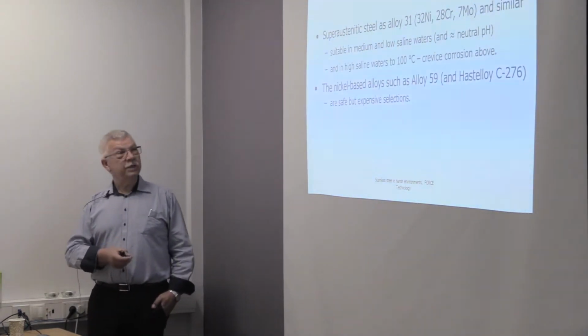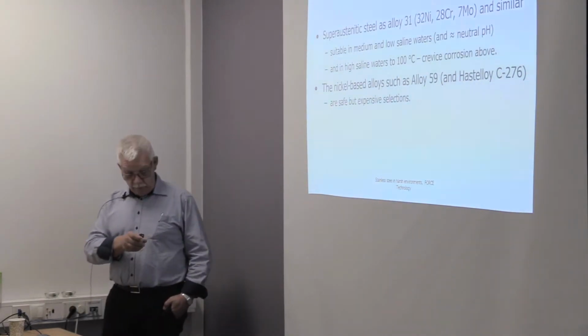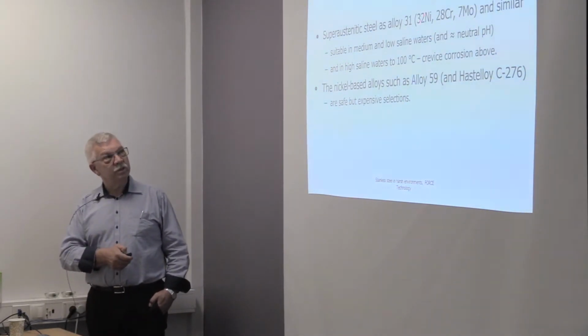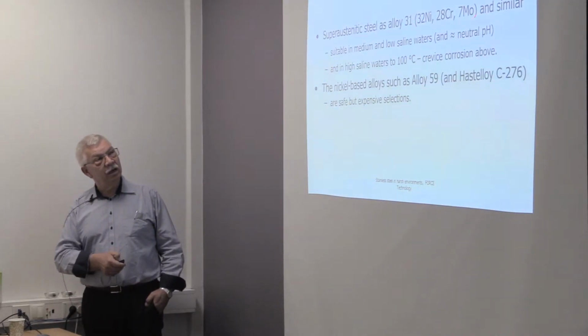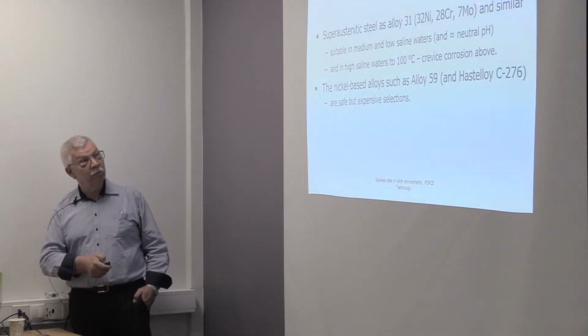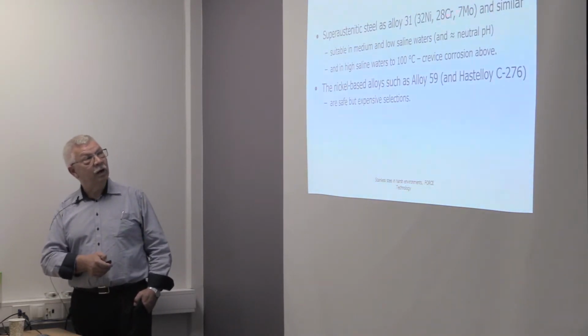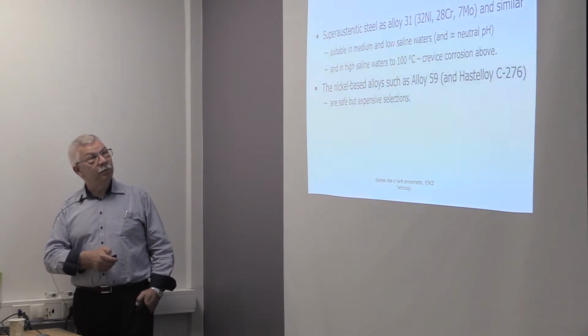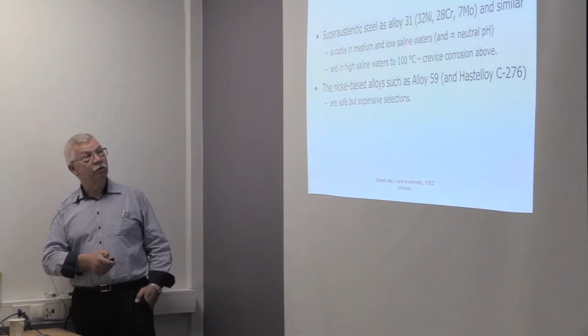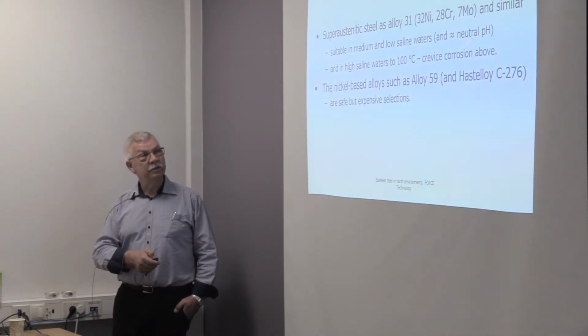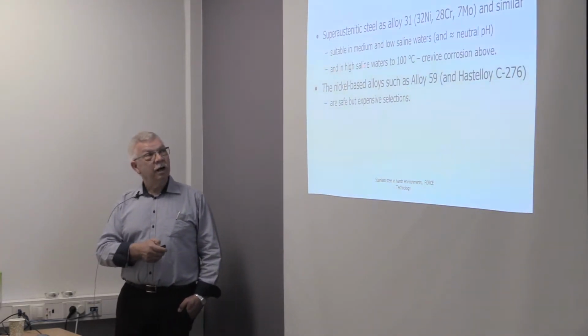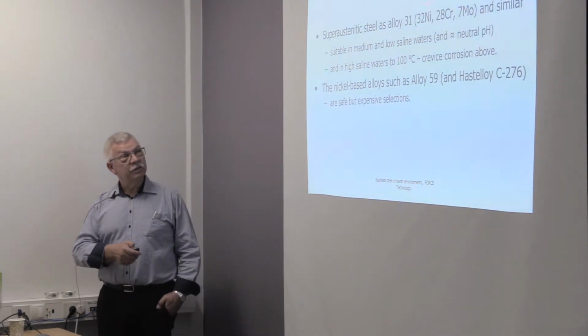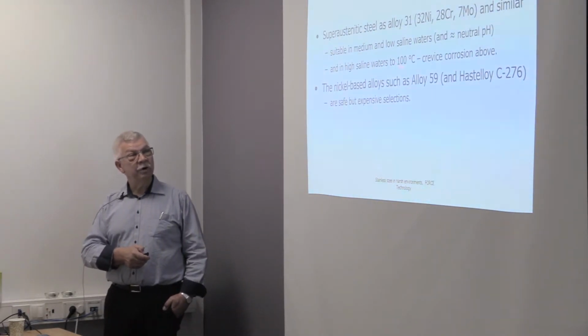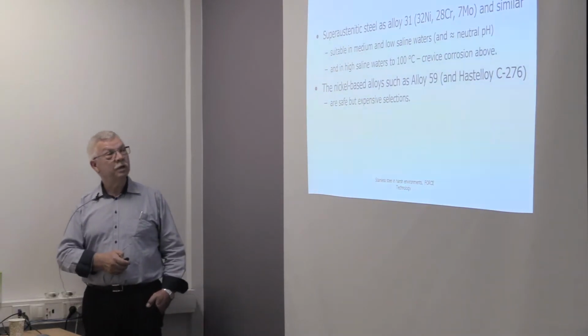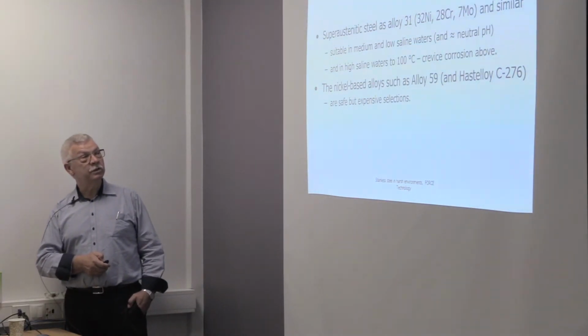Even for higher alloyed materials like this alloy 31, which is pretty close to another, Sanicro 28, which doesn't have that much molybdenum, but still, those are higher alloyed materials, and they would be suitable for medium and for low salinity and still neutral pH. At higher salinity, the temperature limit for this alloy would be 100 degrees C. Above that, we will have crevice corrosion if there are any crevices in the system.